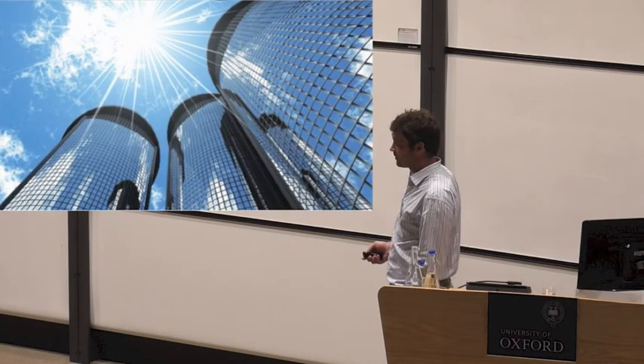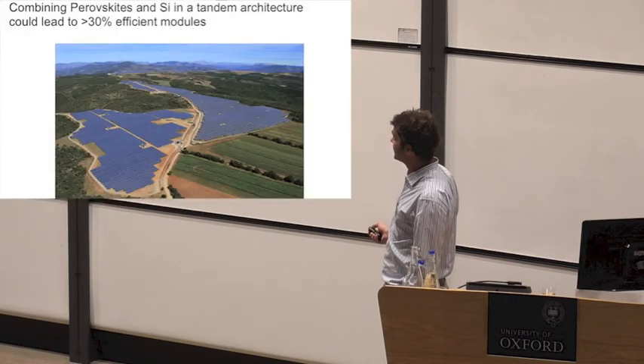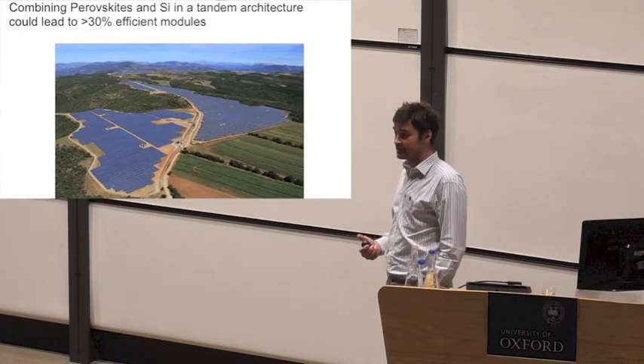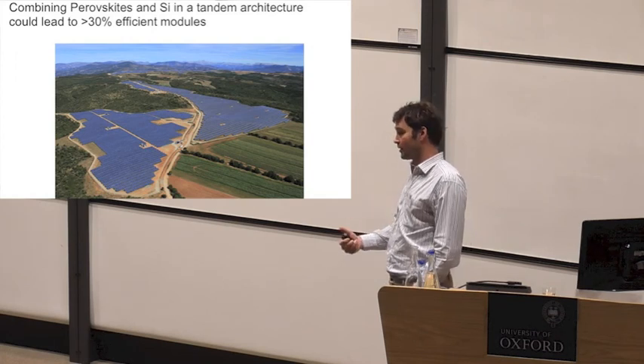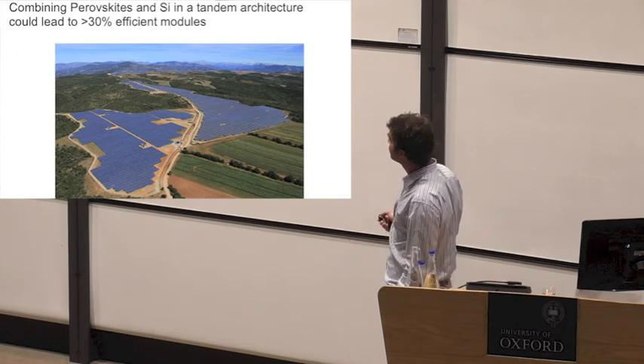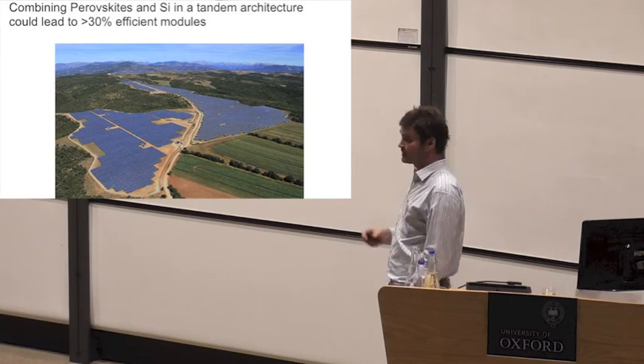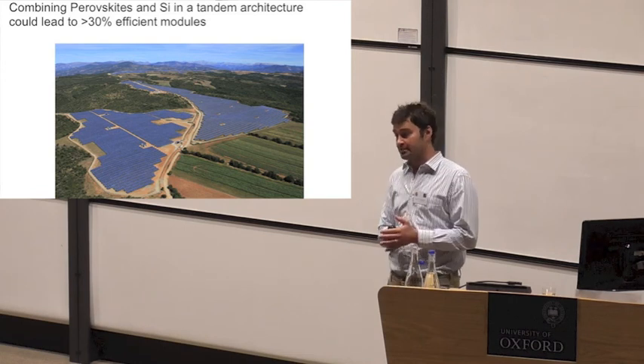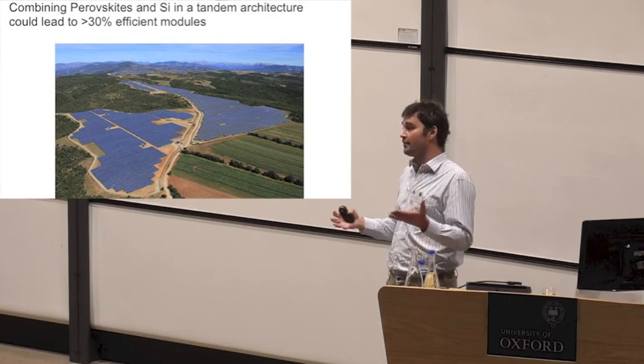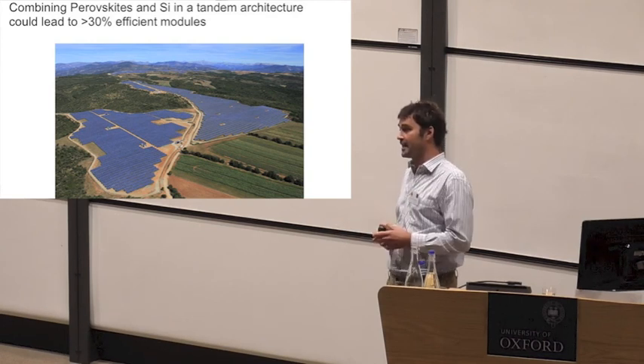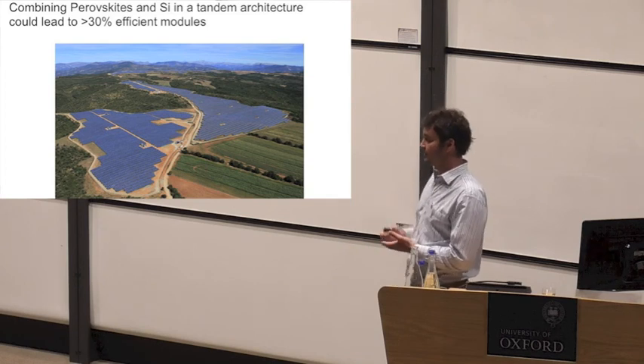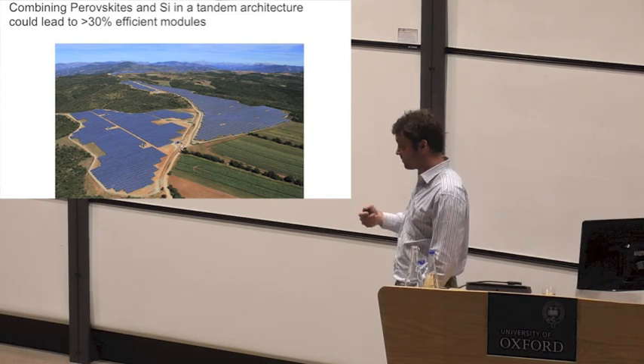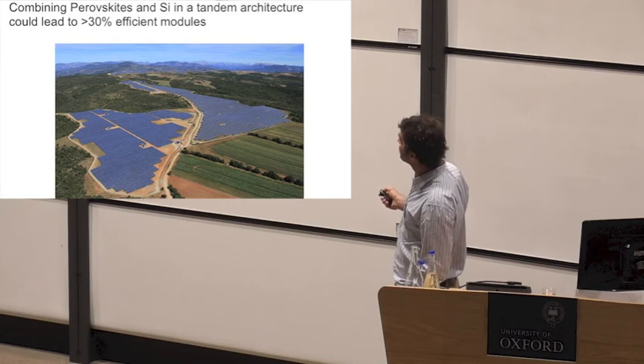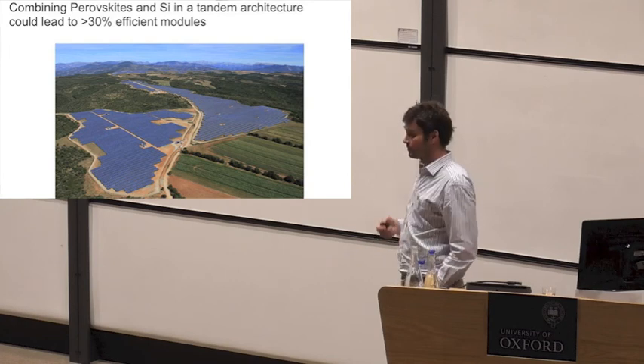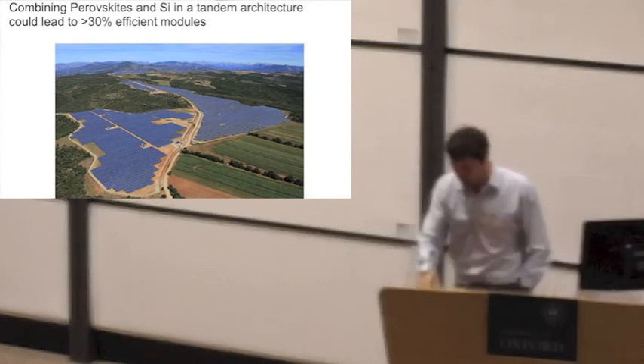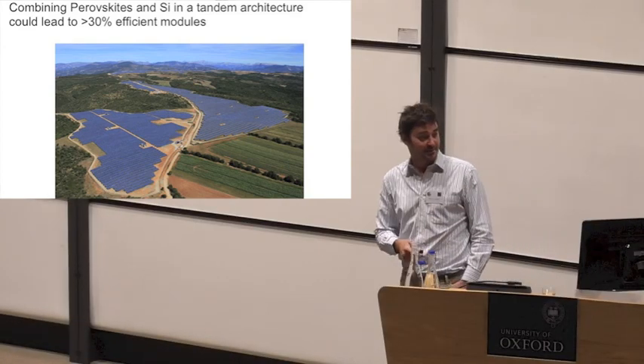One is building integrated photovoltaics. The other is utility PV. Of course, when we match the efficiency of silicon, it could in principle drive down a lower cost PV, and that's what we're really interested in. As well as that, we can make a wider band gap. So we can absorb the visible region of the spectrum in these solar cells and generate a higher voltage and stick that on top of silicon. It's called a tandem solar cell. And that could step up the efficiency. So as well as not inducing very much extra cost, we could end up delivering, in principle, 30% modules, which would be a big improvement. Now, of course, I'm being entirely biased and optimistic here, but we'll see where we get.